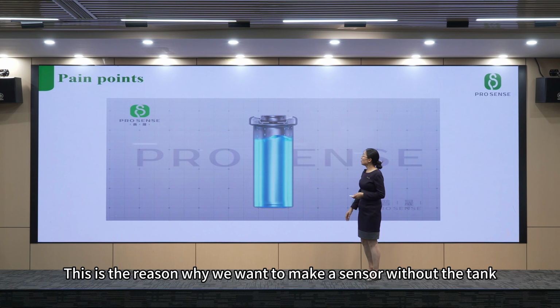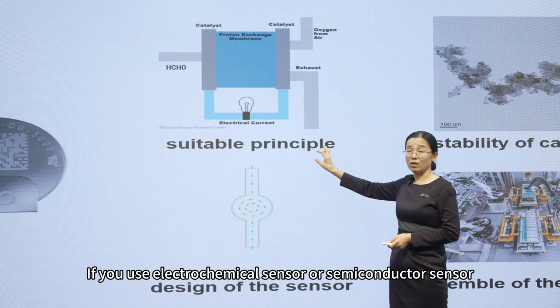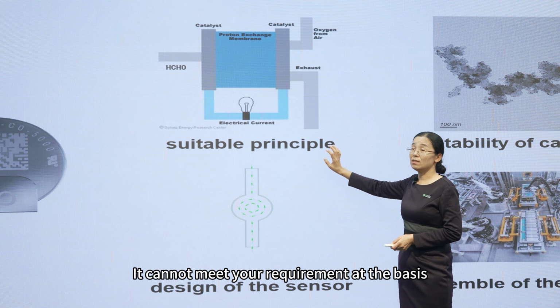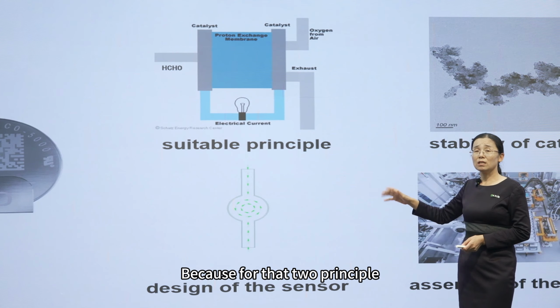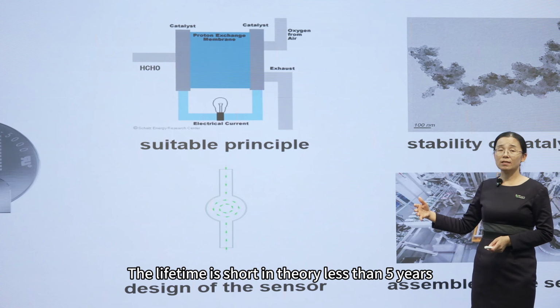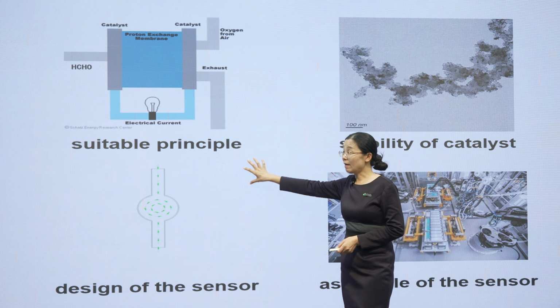For a sensor, I have introduced the background and how we can judge the stability of the sensor. The stability of a CO sensor is determined by several factors. The first one is the principle. I think it is the basis, because if you want a sensor with a long life, more than 10 years, an electrochemical sensor or semiconductor sensor cannot meet your requirement at the basis, because for those two principles, the lifetime is short in theory, less than 5 years. Electrochemical is usually 2 to 3 years. So if you choose an unsuitable principle, everything is wrong.